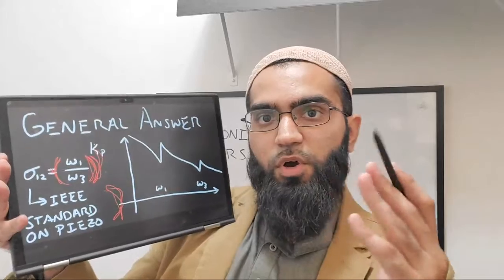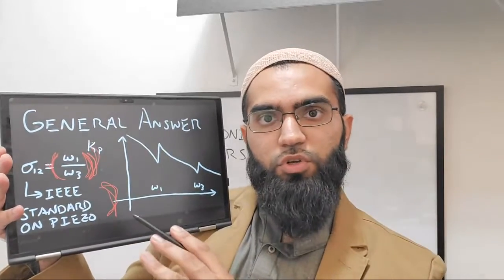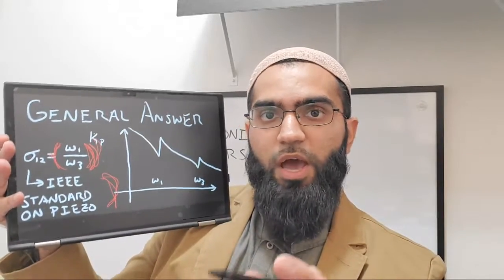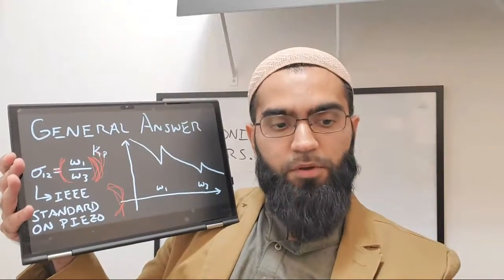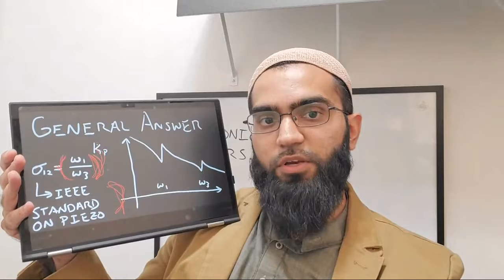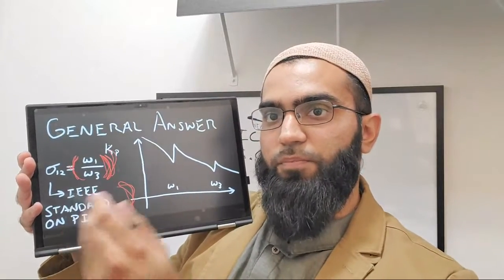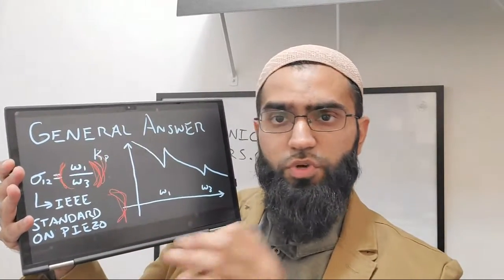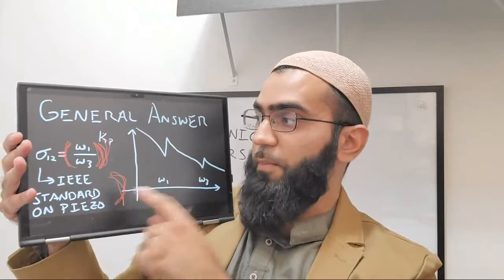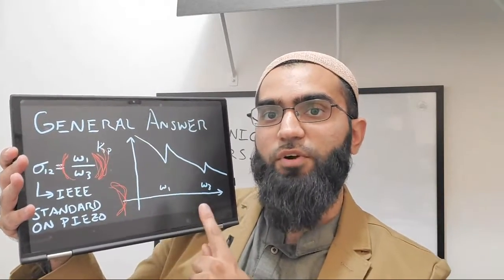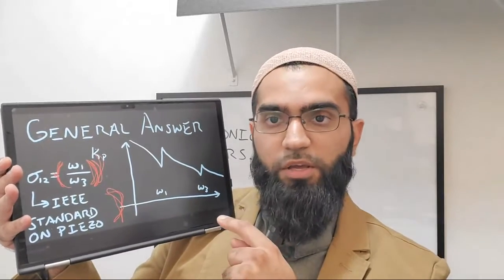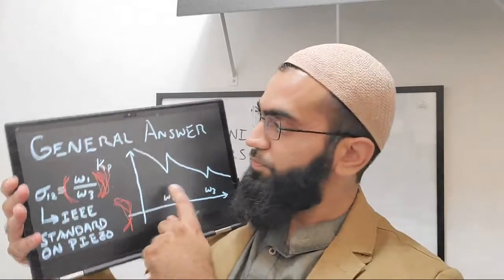So once you're able to do this, you'll then be able to calculate S11 that you would normally do from your length, your rectangular bar, and then you also have another ratio, the Poisson's ratio, so you get an additional factor from this analysis. So this is how you interpret the first and the third, the next occurring harmonic in this sequence.